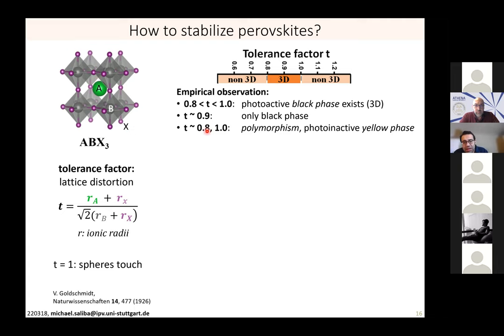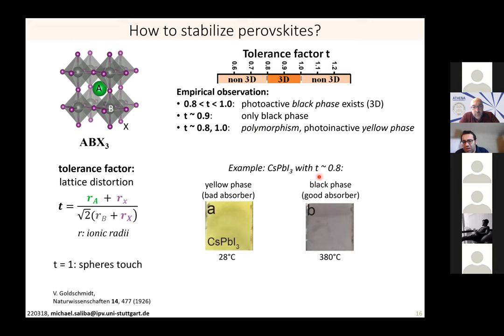Then, of course, being close to the boundary of the empirical relationship means we introduce polymorphism, so the coexistence of multiple phases. And for simplicity, the photoinactive phase is called a delta phase, but we refer to it as a yellow phase because of its color. And we see it here, cesium lead triiodide, which has a tolerance factor of 0.8, has two phases at room temperature. Unfortunately, this is the yellow phase, and only at higher temperatures, going beyond 300 degrees, all of a sudden a black phase emerges. And now the question is, how can we make this exist at room temperature already? And you can see why we call it yellow and black phase from this image.